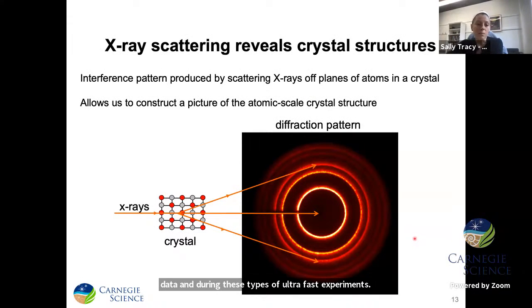So the primary experimental method that we use at these facilities is called X-ray diffraction. With this method, what we're effectively doing is studying the interference pattern that we collect when we scatter high energy X-rays off planes of atoms in a crystal structure. Using this technique, we can take a series of rapid images, which allows us to construct a picture of the atomic level crystal structure and bonding of the material and see how that evolves during the compression and release process.